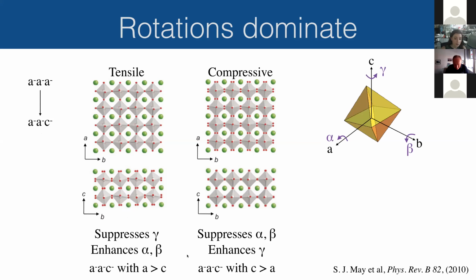The reverse is true for a compressive strain: C is now bigger than A, gamma is bigger than alpha and beta, in other words. So you have now quite a high rotation around the C-axis and almost no rotation around the A and B axis. So this is just to accommodate the biaxial strain. It's not too surprising if you think about how the octahedron can rotate to change its overall volume in space.